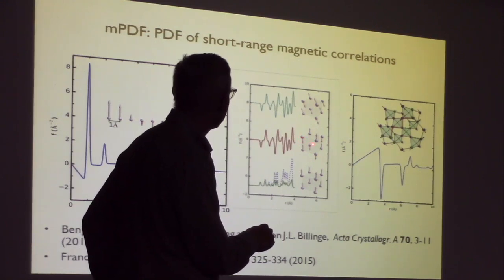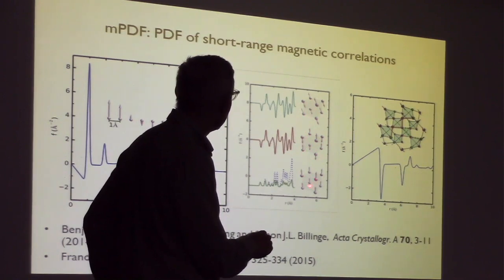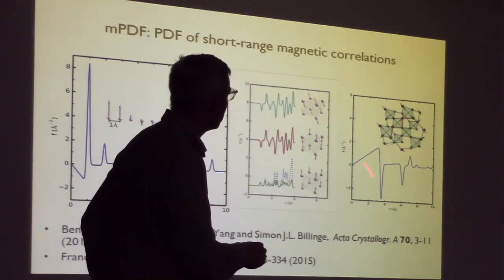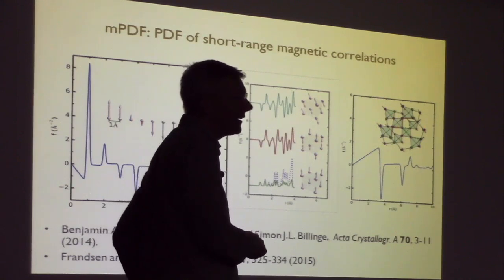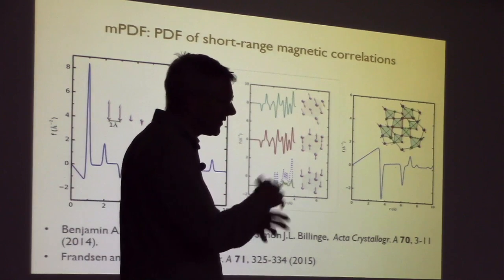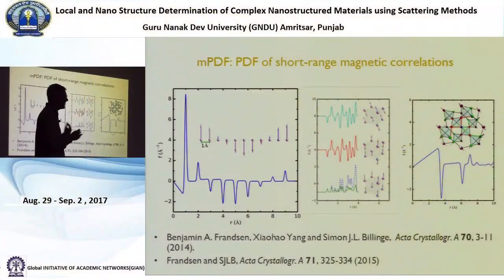This one is some anti-ferromagnetism. So basically we know how to compute them. This one is a very interesting one, which is a spin ice on a pyrochlore. So a pyrochlore lattice is one which has a very high degeneracy and the magnetic spins get confused. So it's a geometric frustration. So if you have anti-ferromagnetic spins and you go around a triangle, you go up, down, and then the third one in the triangle is correlated with both of these. It can't decide whether to be up or down. So we say it's frustrated.